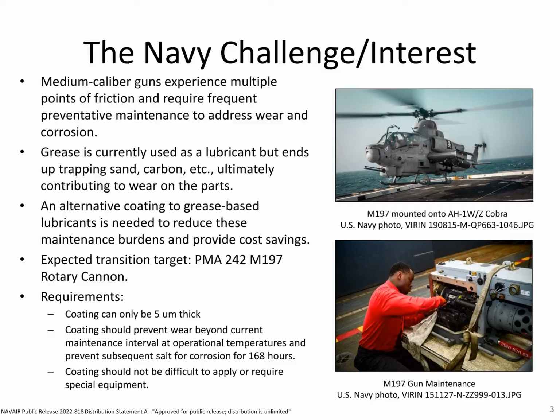A few other restrictions that we've placed on ourselves is that the coating should be easy to apply. So for this reason, we are exploring solution processed applications such as dip or spray coating. Many thin solid lubricant coatings are applied through vapor deposition, which can require expensive equipment. Sometimes it's also difficult to coat things that are not line of sight, whereas with dip coating or spraying, you can get into nooks and crannies that can be difficult to access through these other methods. Solution processing is also, depending on the material that's used in the solution, can be a lot less expensive than some of these other coating methods.